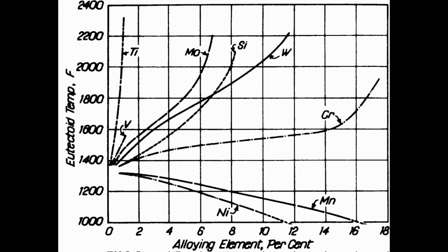Another thing I want to discuss is why there are not more nickel steels. So, these nickel steels, they seem to be pretty great for properties. Why aren't we adding nickel for toughness to more steels? Well, there are a couple major reasons. One is that nickel reduces the temperature where steel transforms to austenite.